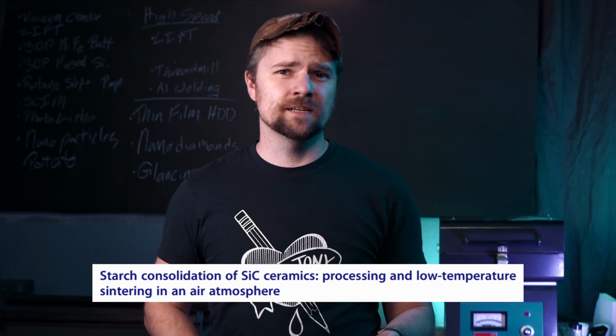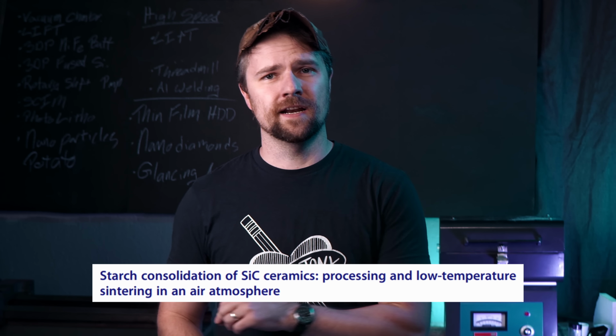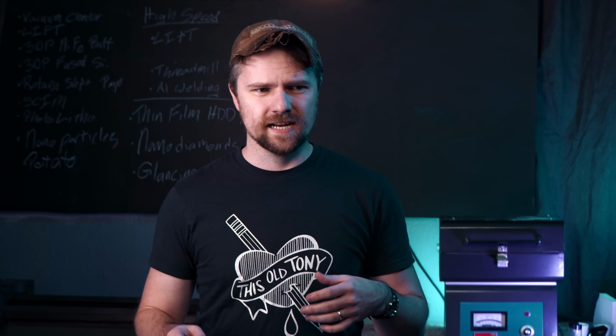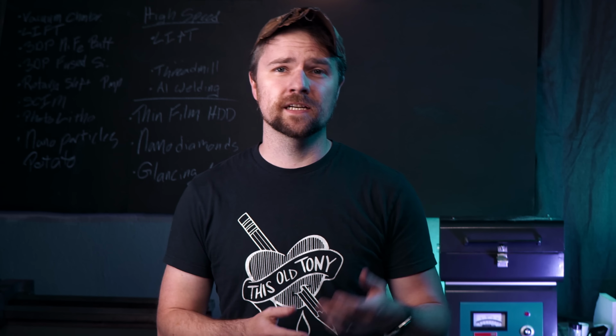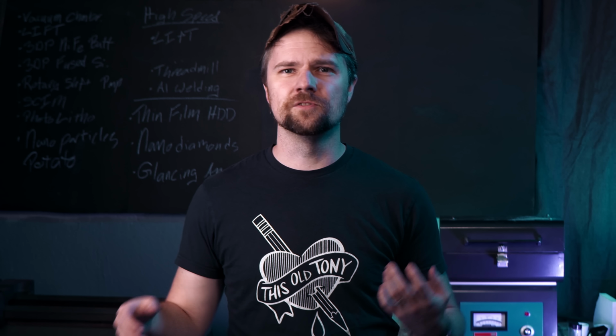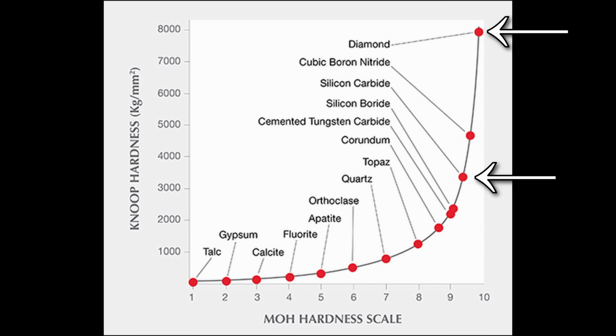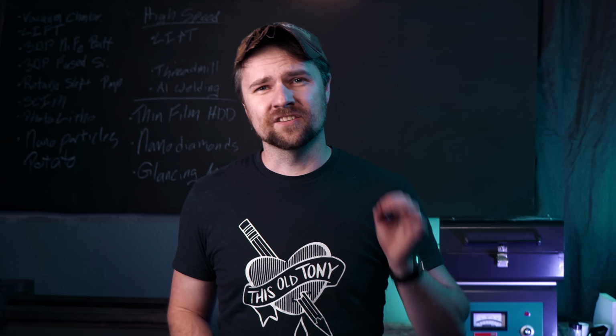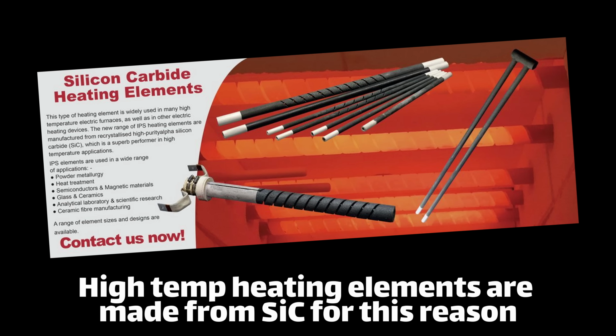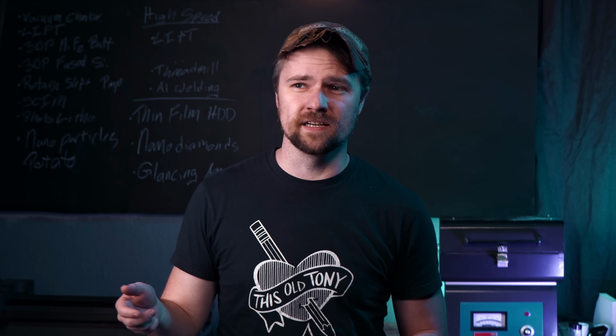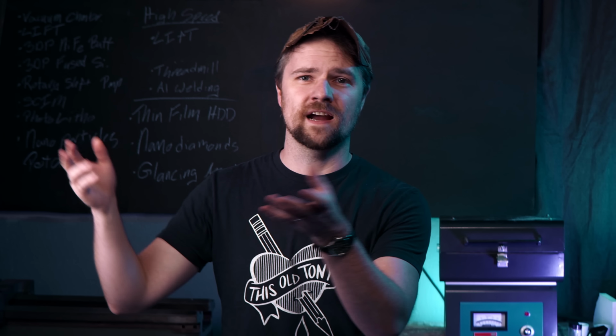So this paper is interesting because it's sintering silicon carbide at a very low temperature, 600 degrees Celsius or thereabouts. And that is very interesting because silicon carbide is a fascinating kind of super material. It's incredibly hard, almost as hard as diamond. It's chemically inert. It has extreme heat resistance. Up until about 2700 degrees Celsius, not a whole lot happens. It just sits there kind of baking in the heat. And then above 2700 degrees, it just sublimates away. It vaporizes into the air.